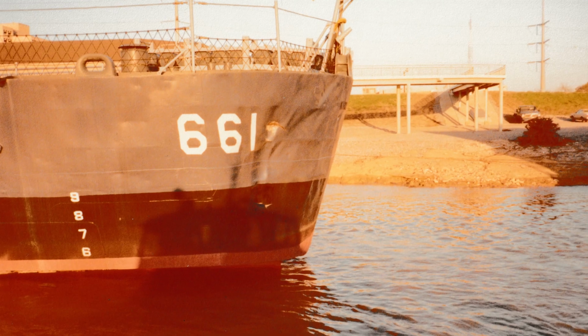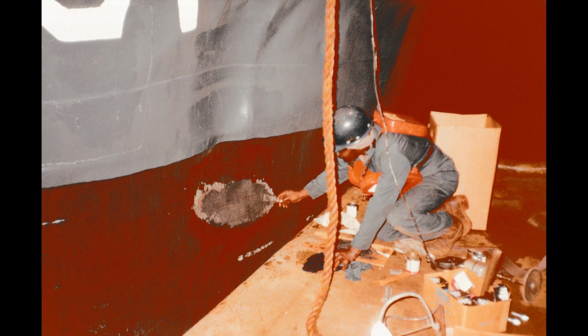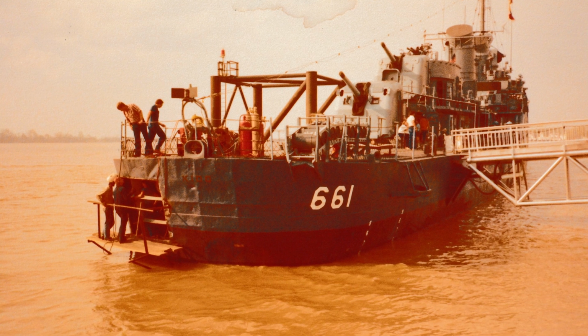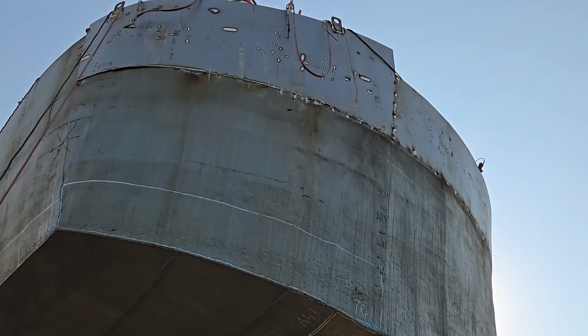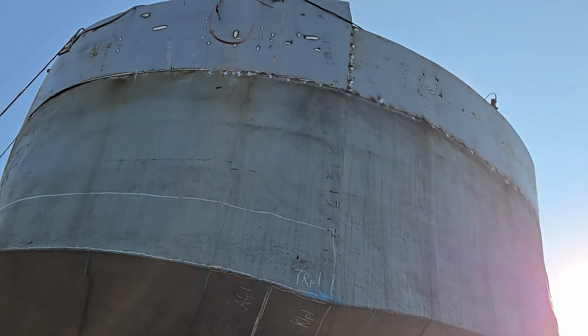It is possible that the collision caused more extensive damage than was thought at the time, with microfractures extending over to the starboard side. Those fractures may have eventually been exposed to moisture from condensation over the years that finally culminated in the rust bloom erupting from beneath the paint. ThomaSea has replaced the affected steel and is completing welding in that area.